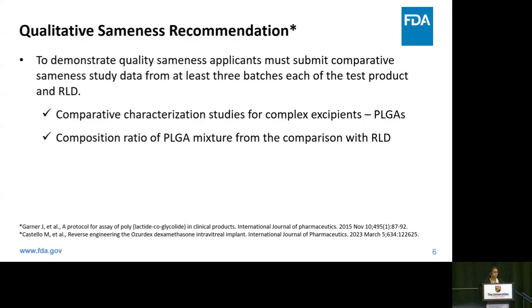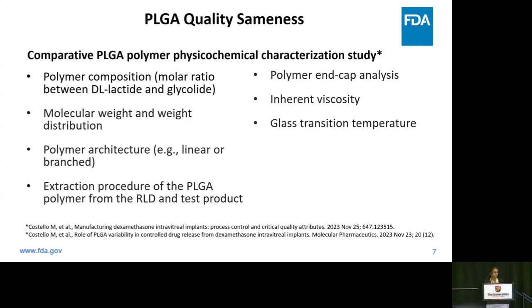Now, the quality sameness recommendation: to demonstrate the quality sameness, the applicant must submit comparative sameness study data from at least 3 batches each of test product as well as RLD. And this includes a thorough characterization study specifically for the complex excipient PLGA, in which the composition ratio of the PLGA mixture must be compared with the RLD in order to get the sameness evaluation. So the characterization study basically should have the polymer composition, molecular weight and weight distribution, polymer architecture, as well as, to evaluate the quality characterization of the finished product, the polymer end cap analysis, inherent viscosity assessment, as well as glass transition temperature assessment is recommended.